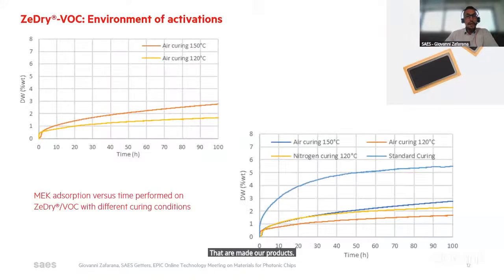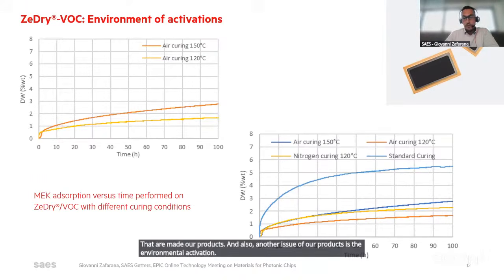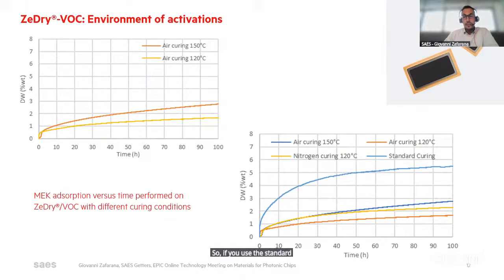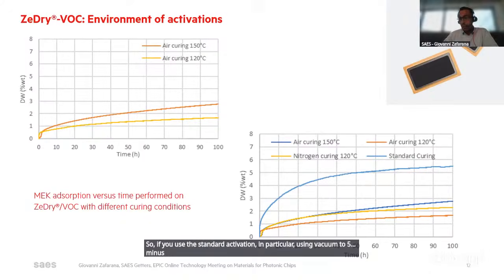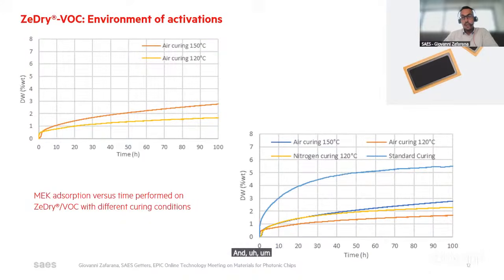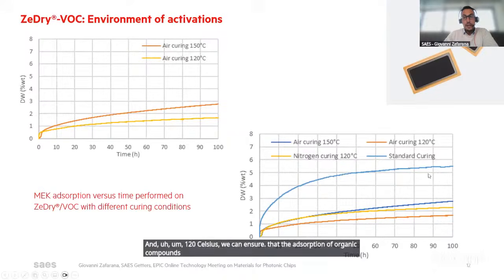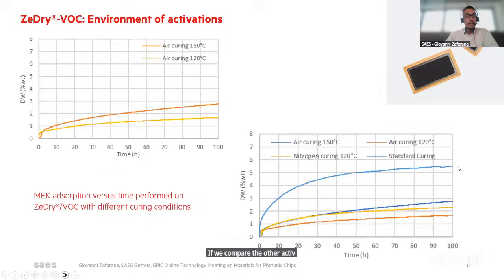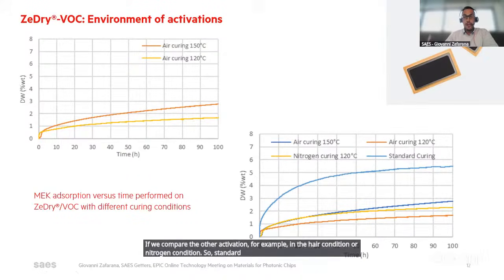Also, another issue for our products is the environment of activation. If you use the standard activation, in particular using vacuum at 10^-5 millibar and 120 Celsius, we can ensure that the absorption of organic compounds can reach the maximum uptake, compared to other activations, for example in air or nitrogen conditions. So standard curing with a high vacuum can ensure a good quality of absorption.